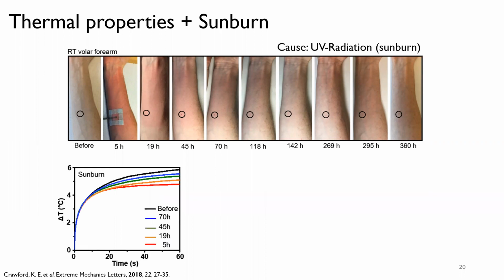When you measure the device in the same spot each time, first, I want you to focus on the black line of this graph at the top. This is before the sunburn. And you would expect a higher change in temperature for the before, because if you remember, the skin has a much lower thermal conductivity, which means it's not dissipating heat as effectively. So it's accumulating, and you expect to see a higher delta T.